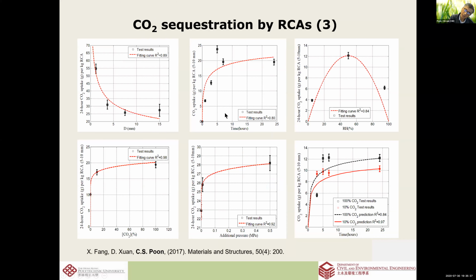And then we try to find out what are the optimum carbonation conditions, because as we said, there are a number of factors affecting carbonation: the humidity, for example, the time, the particle size, the smaller the better, of course, and the time, the longer the better. The humidity, of course, needs to be in a middle range, because you need moisture to help the carbonation chemical reaction, as well as it cannot be saturated, to allow CO2 to diffuse in. So there is also CO2 concentration.